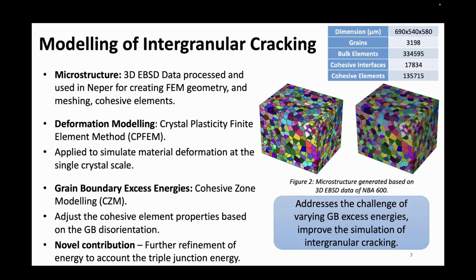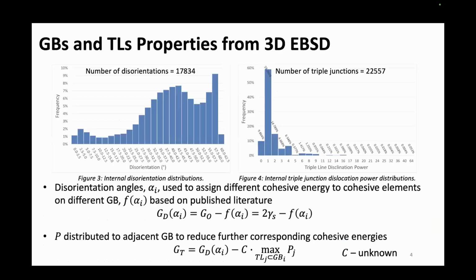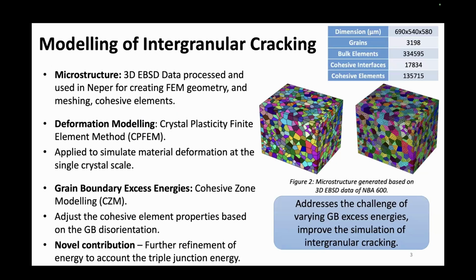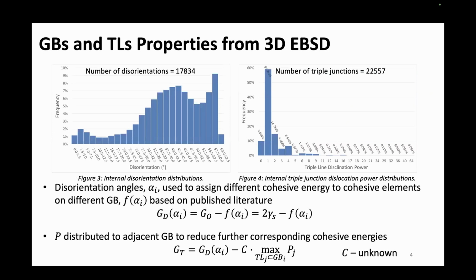For our study, our novel contribution to this field is that we account for the triple junction energy, which hasn't been thoroughly studied before, to further refine the grain boundary energy calculation. With this method, we're trying to address the challenge of varying grain boundary excess energy based on the disorientation and the triple line, trying to improve the accuracy of the simulation of intergranular cracking. So with those 3D EBSD microstructure, here's the distribution of the disorientation and the triple junction disclination power within that microstructure.